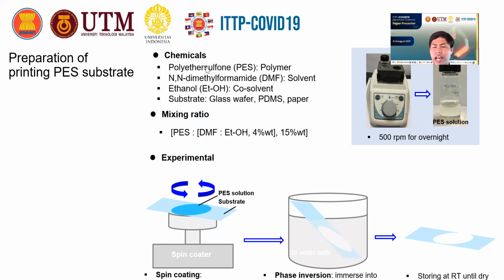Simply, we select a high-temperature stable polymer called polyether sulfone, or PES for short. We mix it with a solvent to dissolve it and make a solution in this ratio. Then we drop the PES solution onto glass or any substrate, spin coat it, and put it in a water bath to separate the polymer and the solvent.